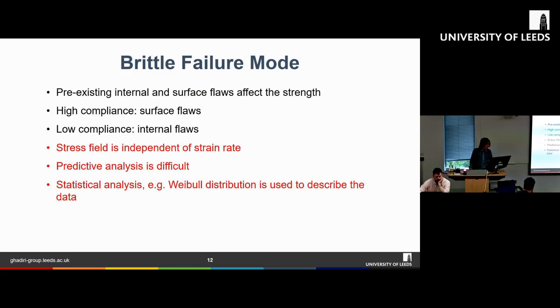So, a quick summary of the brittle failure mode. Pre-existing internal and surface flaws affect the strength of the material. For high compliance materials, failure is caused by surface flaws, whereas for low compliance materials, it is caused by internal flaws of the material itself. The stress field is independent of the strain rate. Predicting the breakage of brittle materials is quite difficult, and mostly people use some sort of statistical analysis to describe brittle failure. The most famous one would be using Weibull analysis to describe the data.